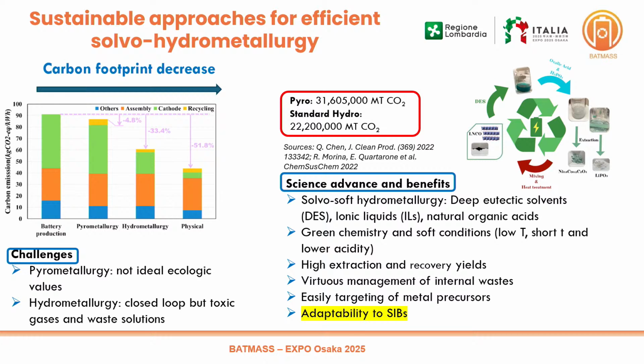Then there is the hydrometallurgical approach, where, as the name says, we are working in an aqueous solution using strong inorganic acids like nitric acid, sulfuric acid and hydrochloric acid. We are able to leach completely the active material present in the cathodic part, obtaining all the critical raw materials in a liquid phase, and with a selective precipitation method we are able to recover 100% of the critical raw materials. This is the most studied methodology until now in the field of recycling, because it shows really good efficiency. But the main issue is the use of strong inorganic acids. These solvents are really not cheap. Also, they have a big problem in terms of environmental impact, because during the leaching we have the production of secondary toxic gas, which also increases the price of the system needed to do the leaching.